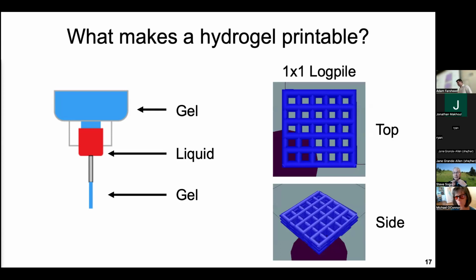And so us as 3D printing nerds like to design some very basic structures to test what we can build that is going to allow us to easily see if this material and printing system is going to work. So right here's what we call a 1x1 log pile structure with 1 millimeter by 1 millimeter pores. And I'm giving you a top view and a side view just to show that we build these up 10 layers tall to really test if we can 3D print, not 2D print like a lot of people do.